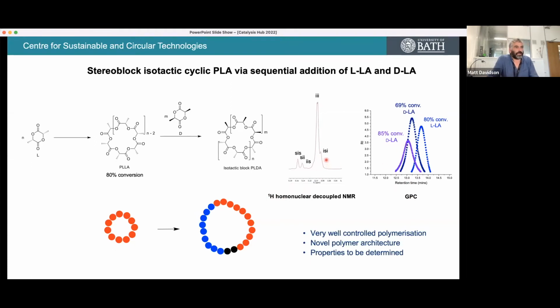If we look at the homonuclear decoupled NMR spectrum, pure isotactic would just have these III tetrads here, but we do see some evidence for heterotactic or atactic polymer in here from these other tetrad signals. And that is actually, when you think about it, exactly what we would expect. So we've gone to 80% conversion, so we still have some of the L monomer present in the reaction mixture here when we add the D. And then we know that we have heterotactic selectivity using this zirconium catalyst.